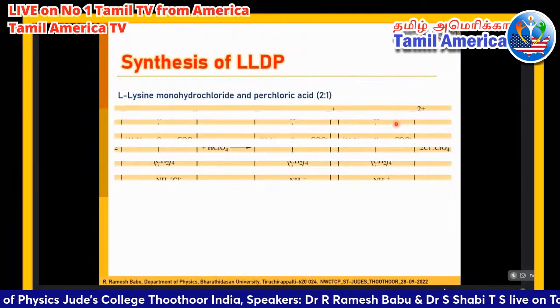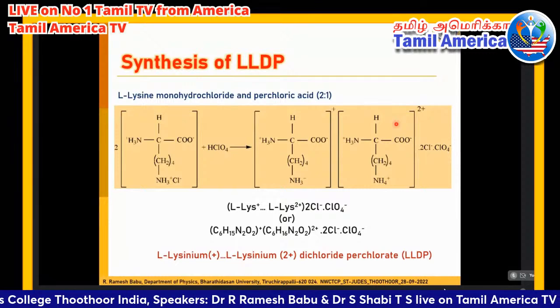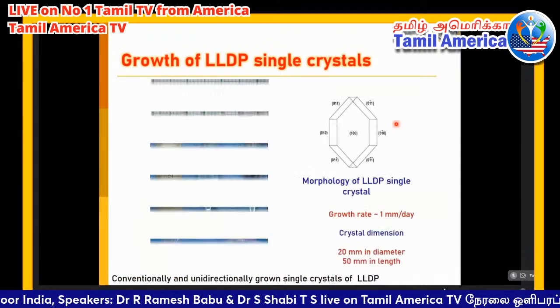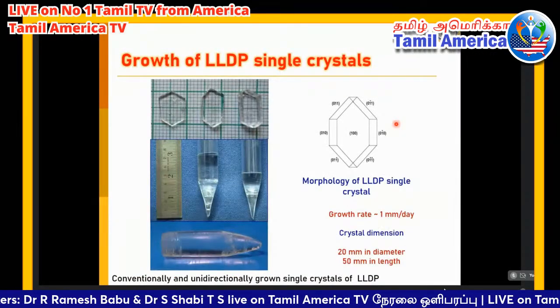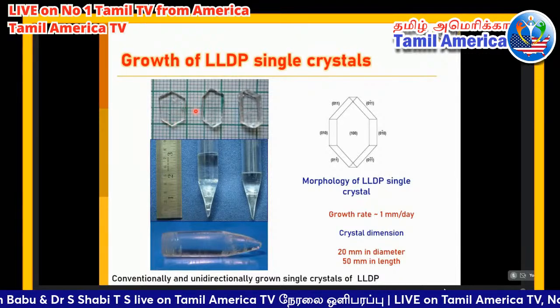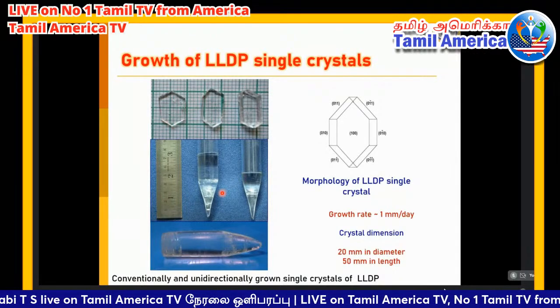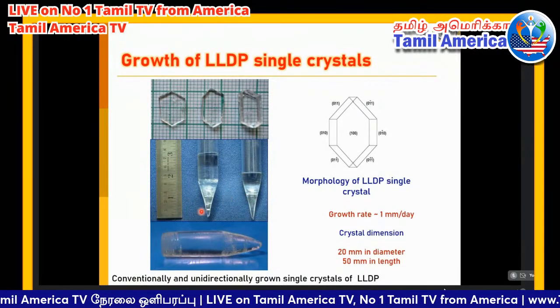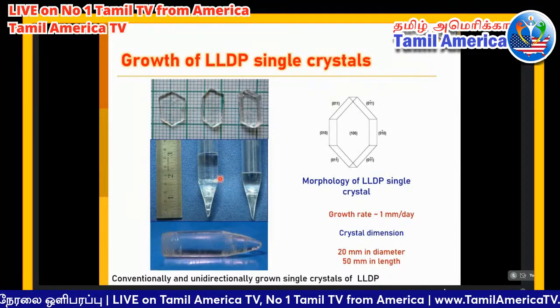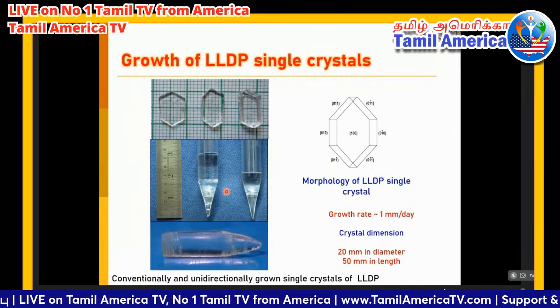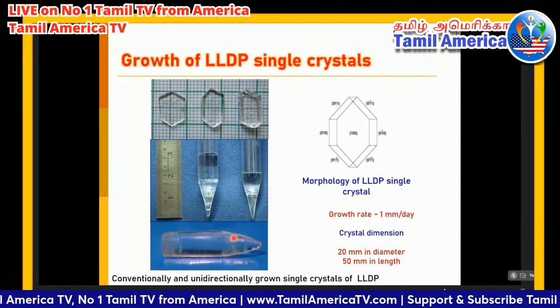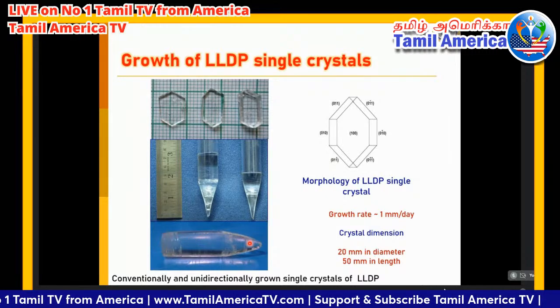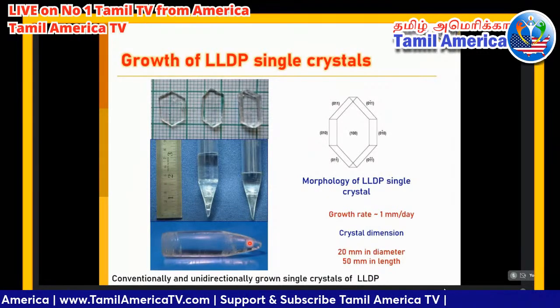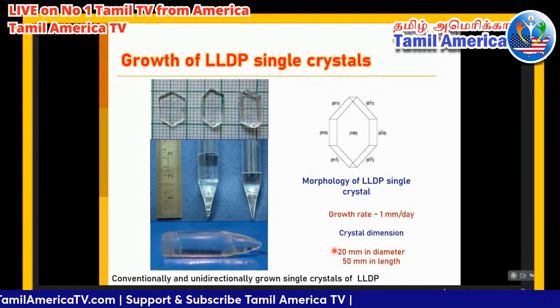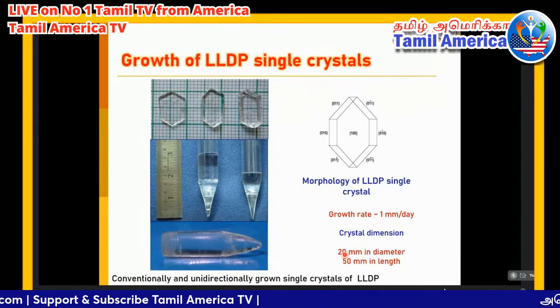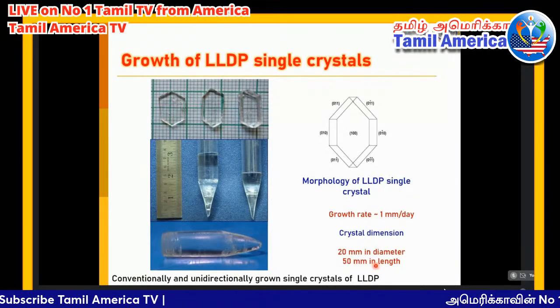Okay. Then for LLDP, the same synthesis procedure was followed. This is the conventionally grown single crystal. Using the conventionally grown single crystal, we have grown bulk single crystals of the LLDP material. So this is the polished single crystal of unidirectionally grown LLDP material. The size is 20 mm in diameter and 50 mm in length.